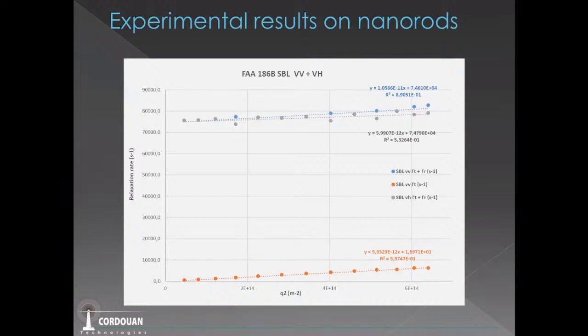This is what we have. On the second relaxation time, you find a line going through zero, which is working very well, and another one parallel to the first one, which is really related. You remember that this distance is 6 times the rotational diffusion coefficient, and the slope of these two lines, which are exactly the same, is the translational diffusion coefficient.